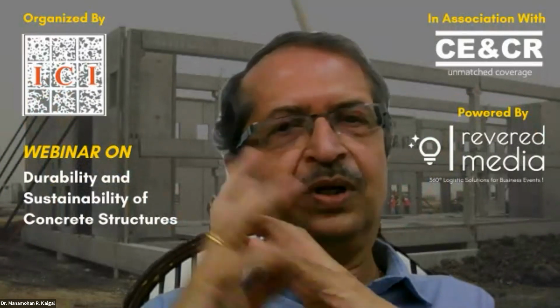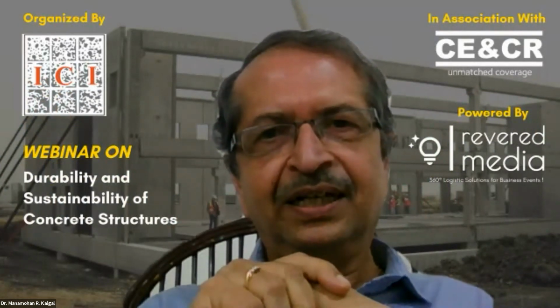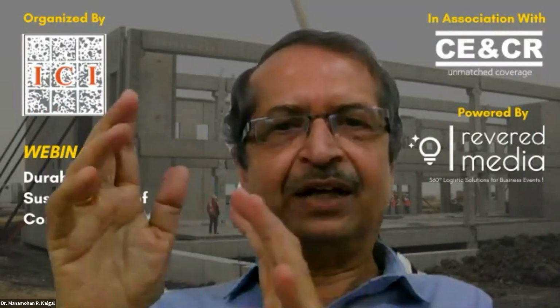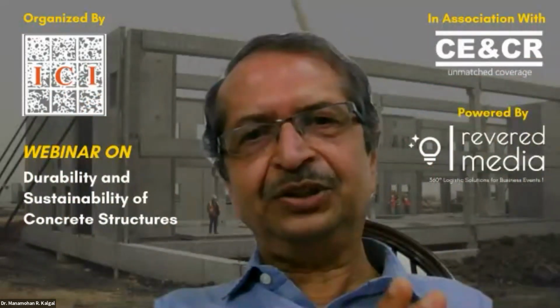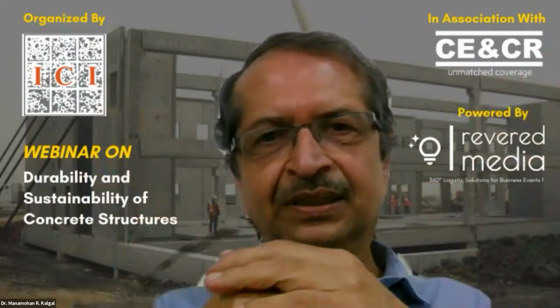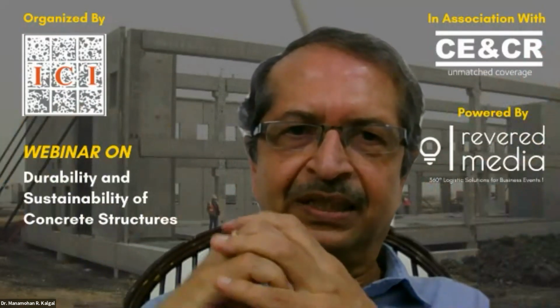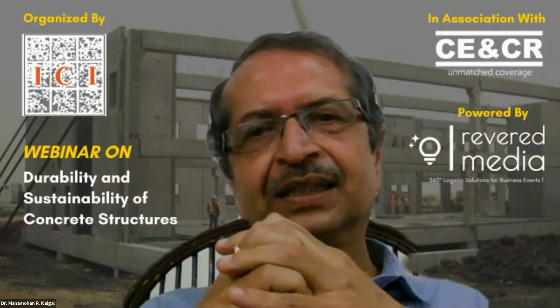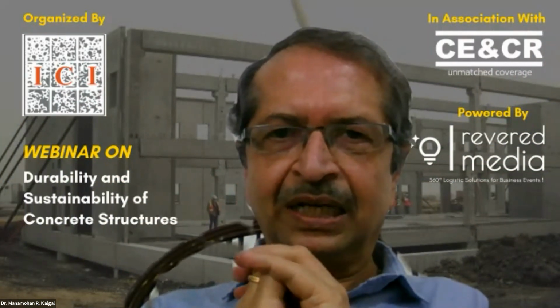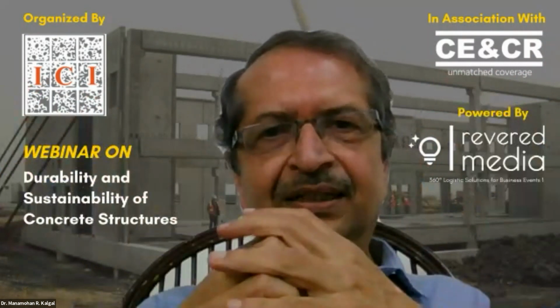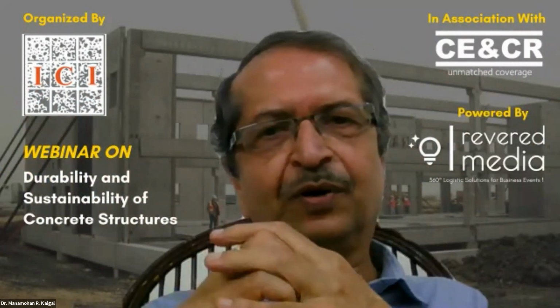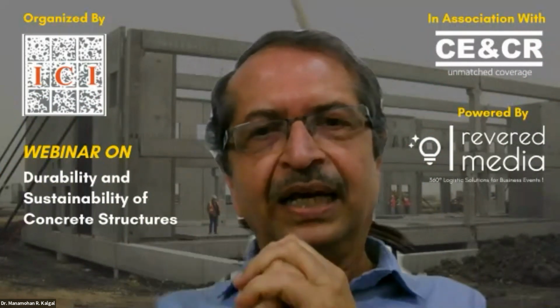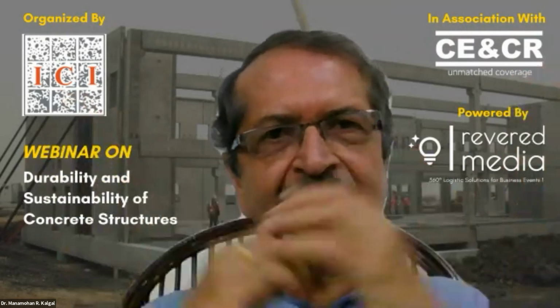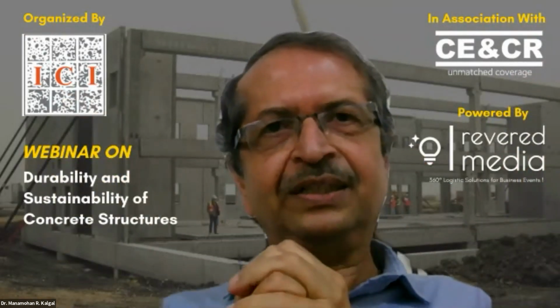Right. So clinker reduction is only by introducing, from the other side, alternative cementitious materials. But one has to be careful when you reduce the OPC content or the clinker content. There are some attendant issues which will come, especially in low grade concretes. In high grade concretes there are no big issues, but because of some issues the BIS is trying to restrict the clinker component to not less than 50%. They want clinker to be present. This of course is debatable, but that is what the mandate is likely to be, either for composite cement or for blended cement or for LC3 and so on. So that is what I would say as far as reducing the quantity of clinker is concerned.